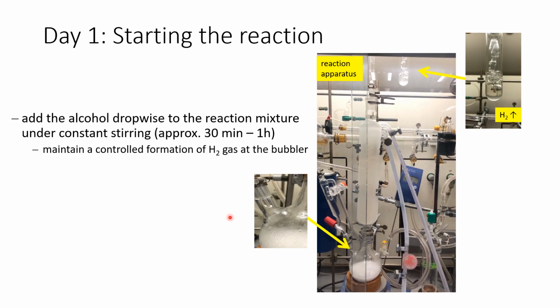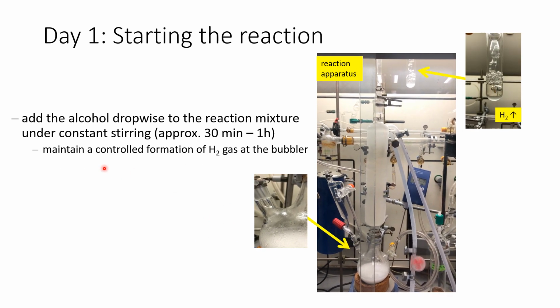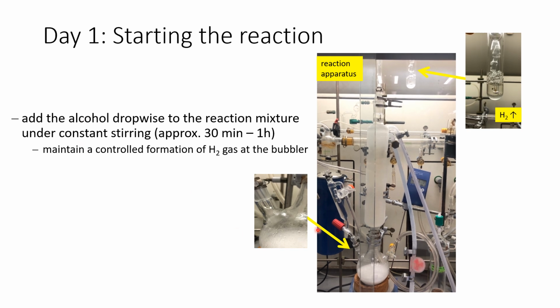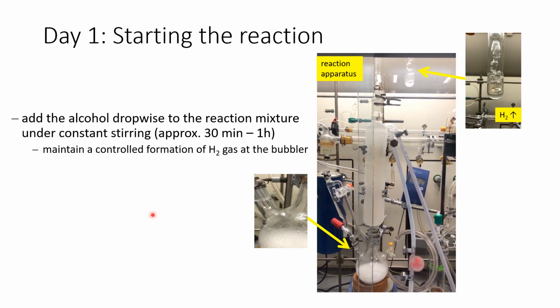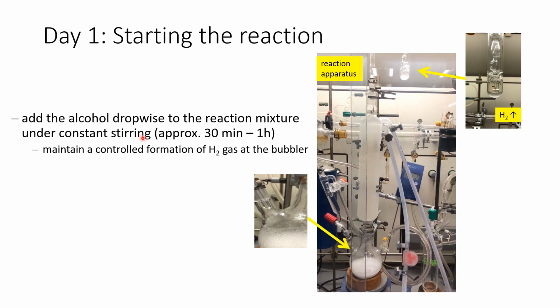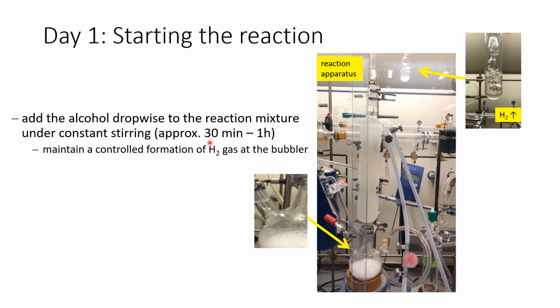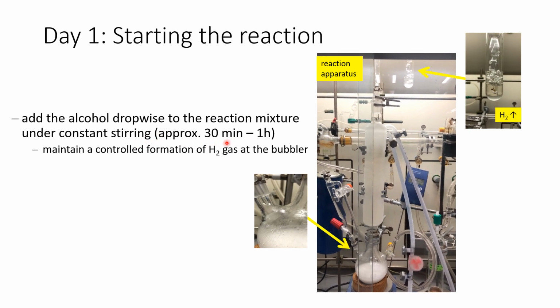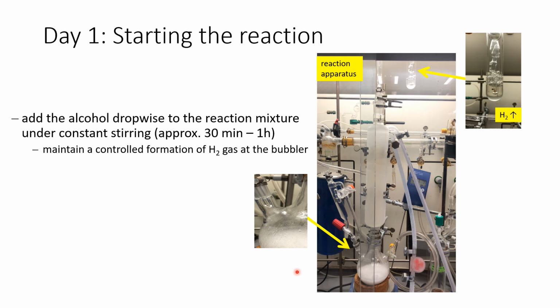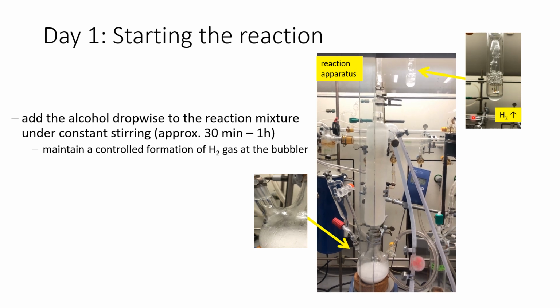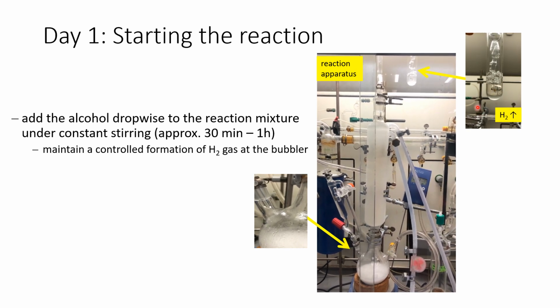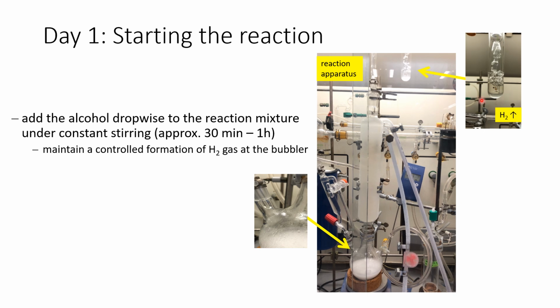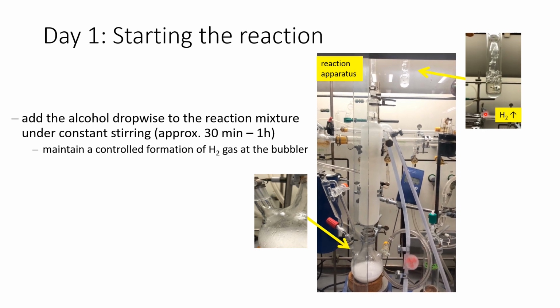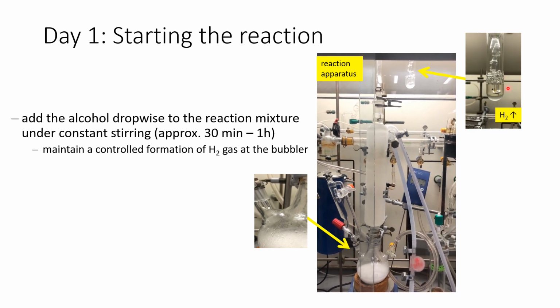Then we can finally start with the reaction. Here, we add the alcohol dropwise through the dropping funnel to the reaction mixture under constant stirring. This takes approximately 30 minutes to 1 hour. Here, we should ensure that we have a steady stream of dihydrogen, which is not too extreme and should be approximately 4 to 5 bubbles per second.